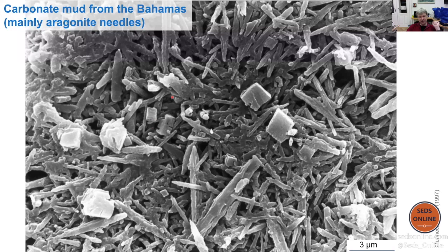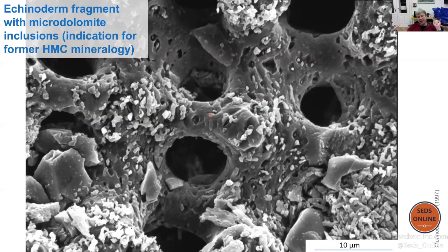aragonite-dominated mud. And if we look closer, this is an echinoderm fragment. And we still see the open pores, so the internal porosity of this echinoderm fragment, the stereom structure. So it's not cemented at all. Normally these pores are filled syntaxially with cement, but when we look at the actual skeleton, we see all these tiny little white dots, and these white dots are microdolomite inclusions. And this means this high magnesium calcitic echinoderm fragment unmixed into low magnesium calcite and microdolomite inclusions. And this obviously happened very early and stabilized this skeleton. So low magnesium calcite is stable, dolomite is stable.